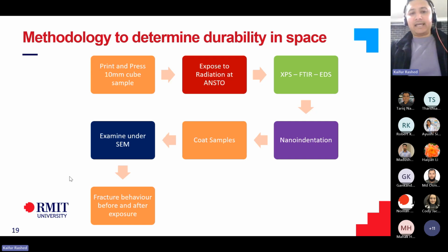But again, this plan failed as well. So after we did nanoindentation, I tried to look at the samples under SEM. But even though we put a significant amount of force, we were not able to see any fracture surface because everything was within the elastic limit of the polymer. So we could not study the fracture behavior.